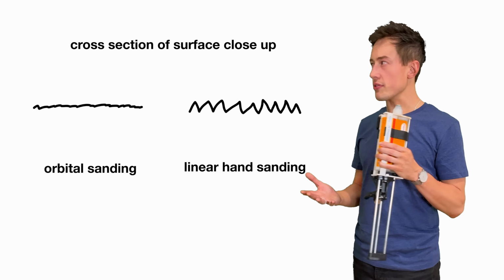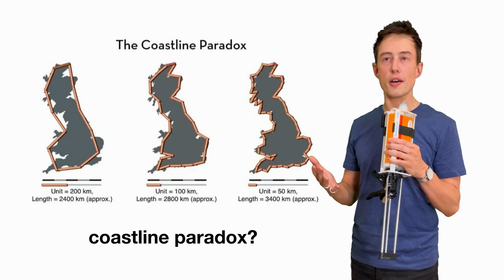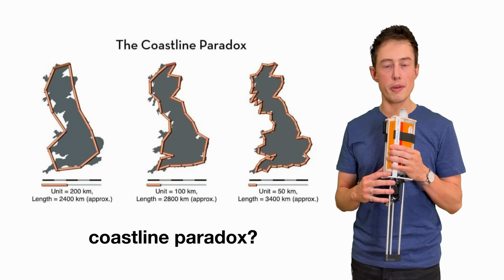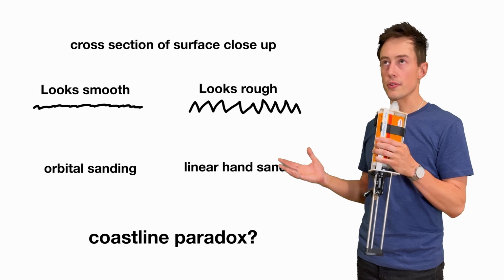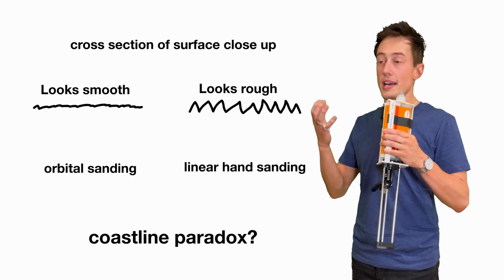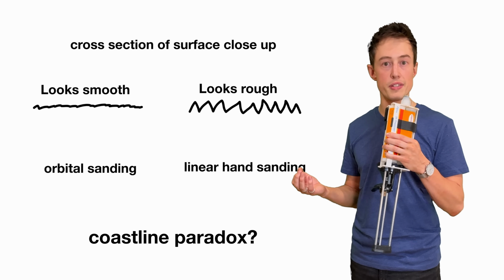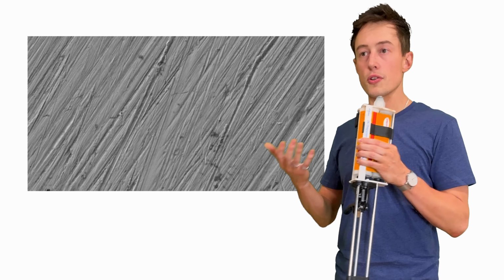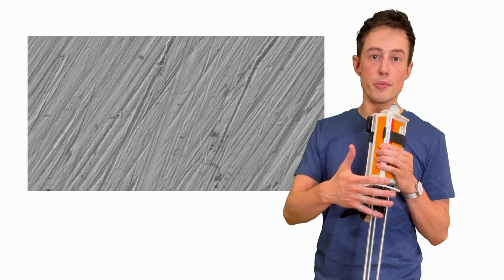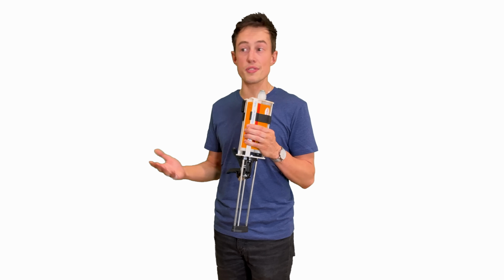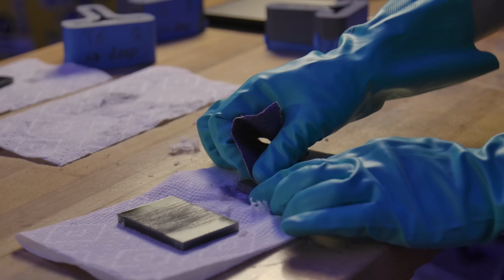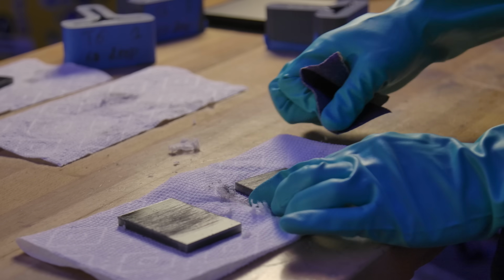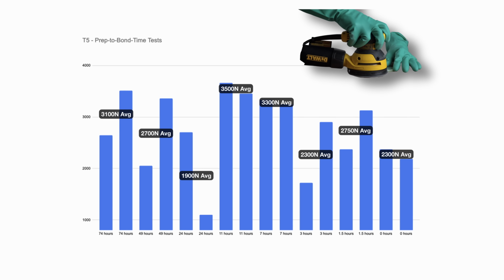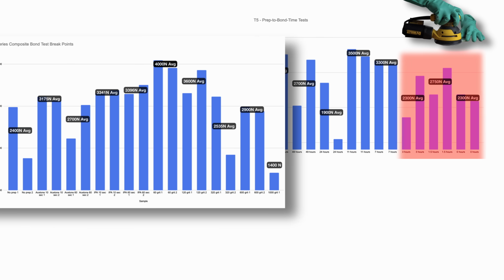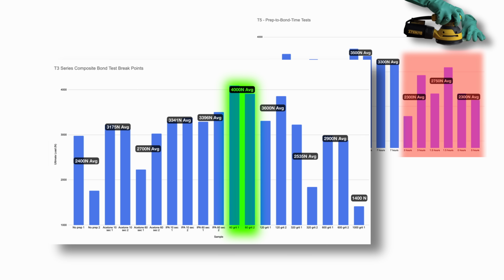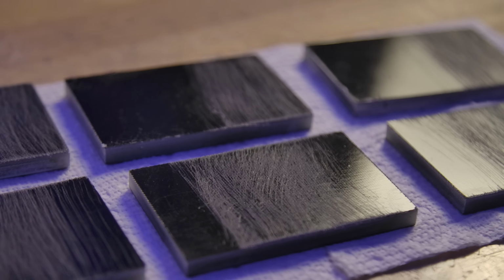I might be falling for the coastline paradox here, and that's always how I've heard it described from experts in composites manufacturing. The surface may look smoother, but it actually has more ridges and, as a result, more surface area than a rough surface. It's just rough at a microscopic level, which means it could be more surface area than a low-grit sandpaper. But once again, if we want to know the answers, let's just run the experiment. I made 3 more coupons that I linearly sanded hard with 60-grit sandpaper. If the orbital sander seems to make it worse, maybe linear sanding is the key to getting back to that 4,000 Newton number, so we'll do that by pressing hard with 60-grit sandpaper.